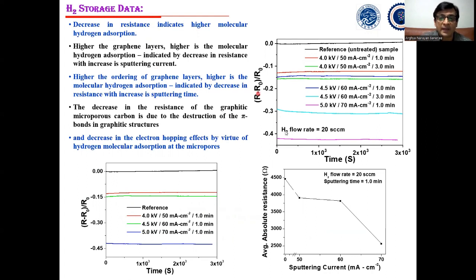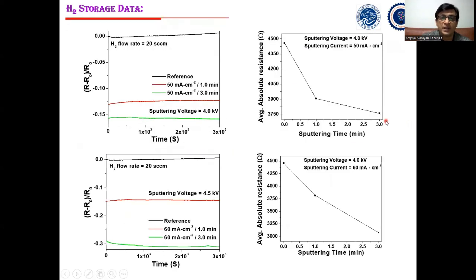And we observed that in a hydrogen flow of 20 SCCM, as the number of graphene layers increases, the differential resistance is decreasing. So with increasing number of graphene layers and increasing ordering of the graphene, hydrogen storage increases. This is what we observed here. So what is the reason behind this? These are some of the other results. You see that with different sputtering voltage, the increase in graphene layers is increasing the hydrogen storage.